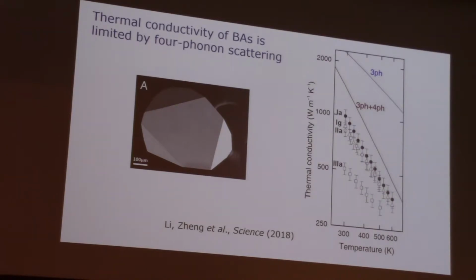Now remember, the prediction was diamond. The prediction was up here, and that's labeled with 3 phonons. So what that means is the original prediction was based on interactions of 3 phonons, so third order anharmonicity. Well, it turns out this isn't good enough. And the experiments then drove the theory people to go farther and include fourth order anharmonicities, 4 phonon interactions. And they're able to predict thermal conductivities that are quite well aligned with what we saw. And now we're going back to working on seeing whether maybe some of the crystals could be a little higher, refining the theory in any way.